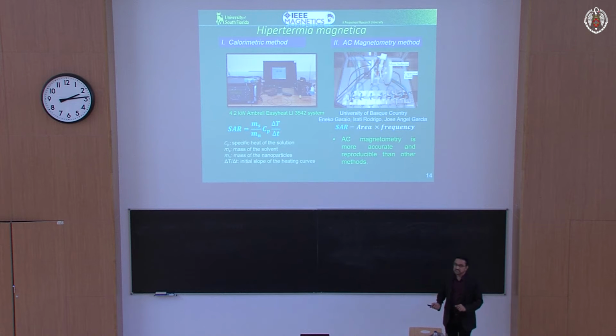So in our lab, we use what is called a calorimetric method to determine the heat generated. So that's our power supply. It's an AC power supply. It's at a fixed frequency of 325 kilohertz, and we can change the AC field amplitude. Remember that the field amplitudes are much higher, very high, not like the ones you have in your SQUID. In your SQUID, the field amplitudes are very small, 10 Oersted. Here we're talking about a few hundred Oersted, up to a kilo Oersted. Okay? So we can generate that. Particles are sitting there. We can actually put a temperature sensor and directly measure the heat. And what we plot here is the change in temperature, or the increase in temperature, as a function of time.